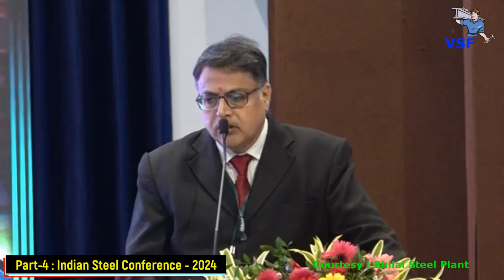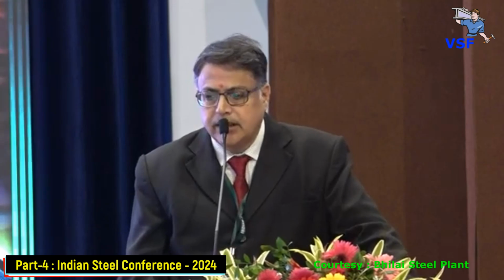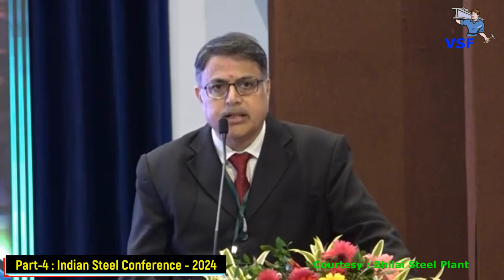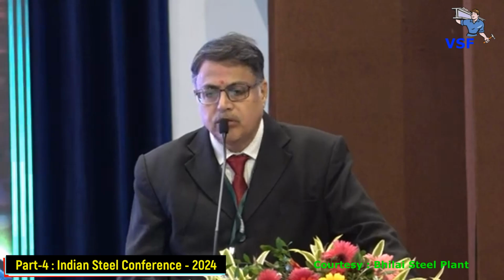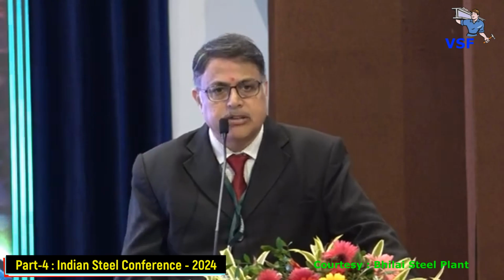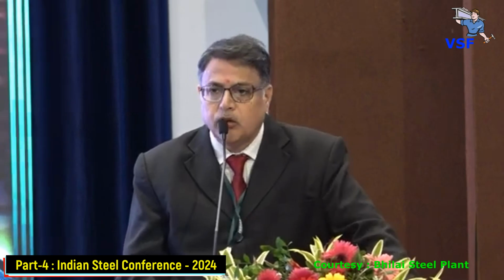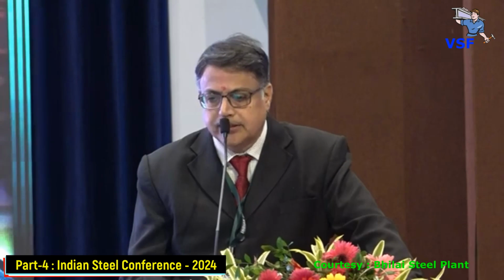And this obviously results in close to 60 kg of CO2 per ton of hot metal reduction. So these are just process efficiency improvements without incurring any capex. So these are some of the sustainable decarbonization initiatives. I will not get into each of the products, it's very long. I would invite all of you to visit our stall here, stall number 6 and 7, and get into the more details. So some of the products which will lead to using our products, we can almost reduce 1.7 million tons of CO2 emissions for SAIL alone, assuming a SAIL production of 20 million tons.